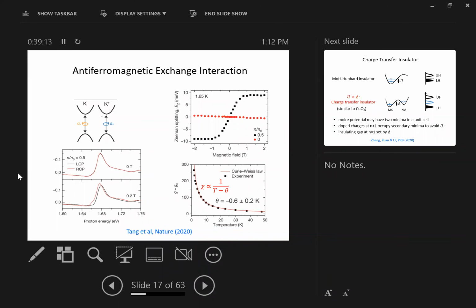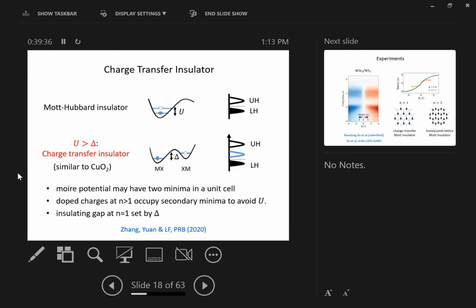And in this fitting, there's the so-called Weiss constant. This Weiss constant is actually negative. In this case, it shows that there's some small residual antiferromagnetic interaction between the spin moments. And that's again consistent with Hubbard physics. In the Hubbard model, t squared over U process of virtual hopping will actually generate antiferromagnetic interaction. The neighboring spins prefer to anti-align rather than align.